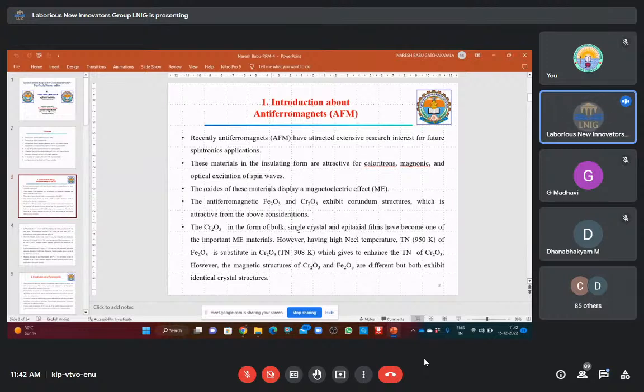magnetoelectric materials. However, having a high Neel temperature, Fe2O3 is substituted in Cr2O3, which enhances the TN of Cr2O3. So when I doped Cr2O3 with Fe2O3, the Neel temperature, known as the TN of Cr2O3, is increased. However, the magnetic structures of Cr2O3 and Fe2O3 are different, but the Neel temperature of Cr2O3 is increased when Fe2O3 is doped with Cr2O3. So that is the thing.